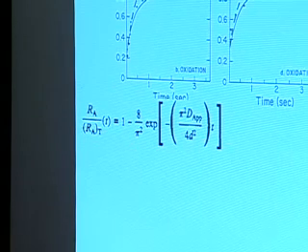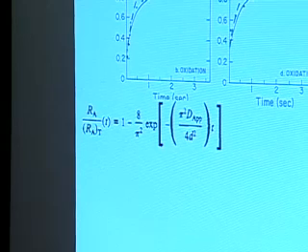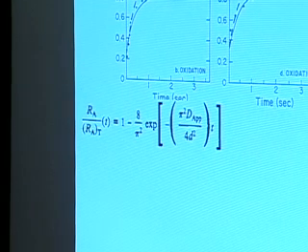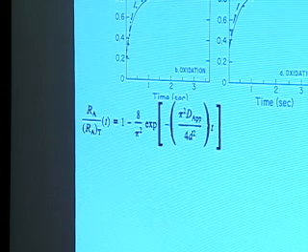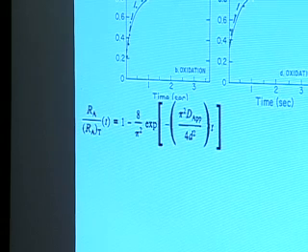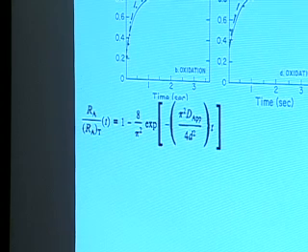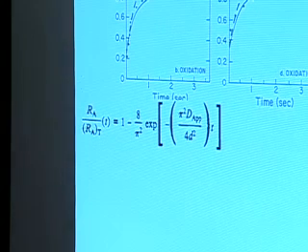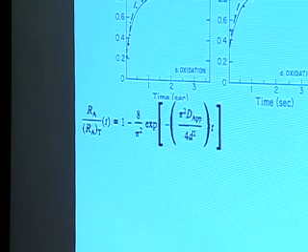And so I said, we're going to fit it to that data, and it's going to work perfectly. It's about as good a fit as the one I'm showing you over here. It does not fit. So now I'm very confused. The system by cyclic voltammetry is reversible. And I know it's reversible because we can do those cyclic voltammograms I showed you 1,400 times with very little change. So it is reversible. Even if you don't believe the diagnostics, it's reversible. And yet it doesn't fit all the standard equations.